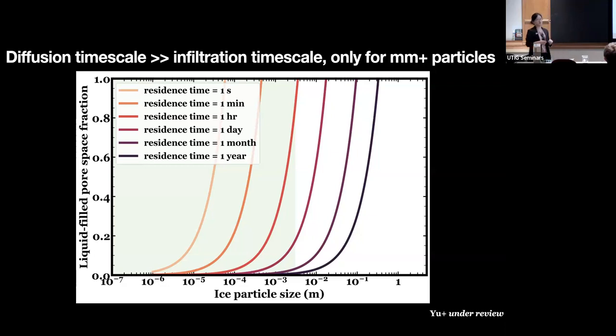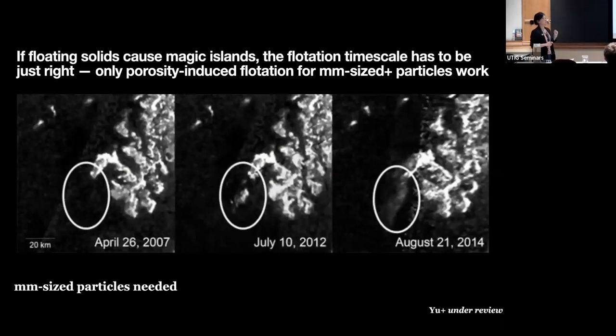So this is literally I discovered this and I have to rewrite the paper and everything. But we think this is actually possible now with porosity-induced flotation, but only for larger particles that are millimeter size. And that tells us something about the origin of these magic islands, because people, again, have proposed a different mechanism to make these magic islands, like the material.